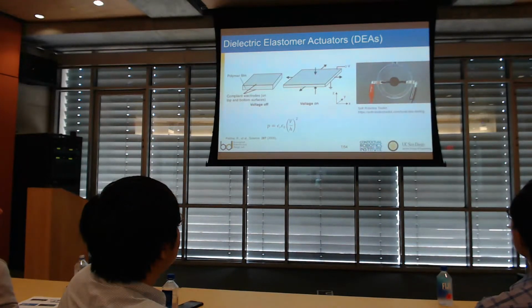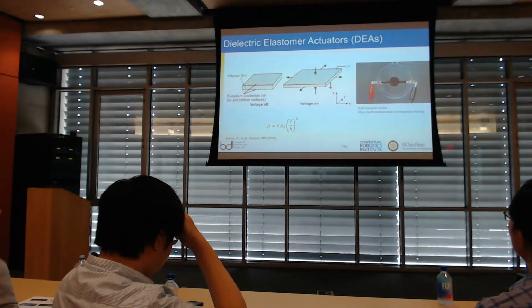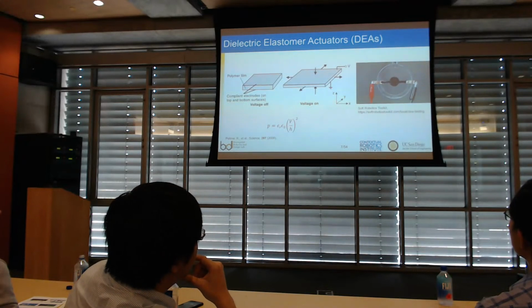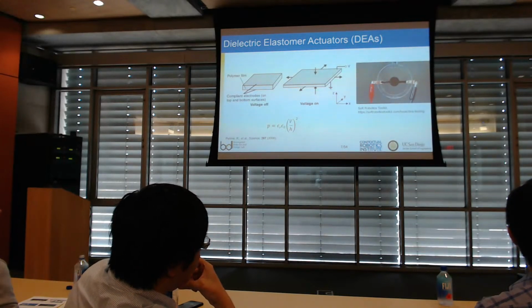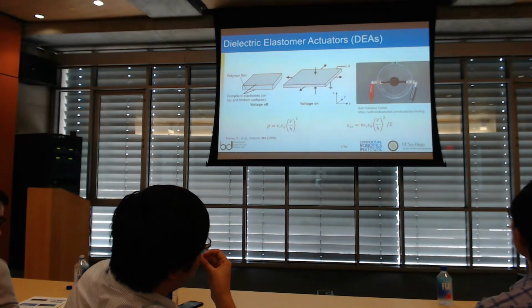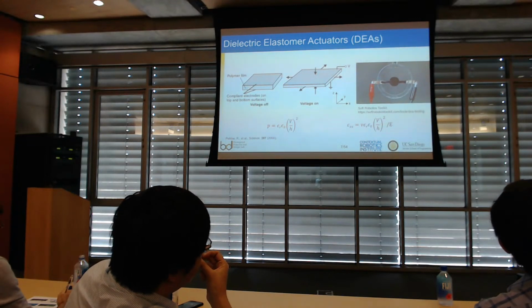And so the pressure that you can generate with these actuators goes as epsilon r, which is the permittivity of the material, times epsilon naught, which is the permittivity of free space, and then it's times the voltage that you apply divided by the thickness of the actuator squared. And then the strain that you get, the amount that it moves, is equal to nu, which is the Poisson's ratio, which is the ratio of how much it deforms in one direction. And then the same components that we talked about earlier, and it's divided by the Young's modulus.